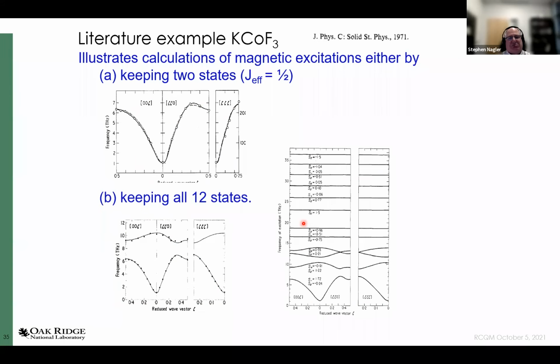So this is exemplified by this material, potassium cobalt trifluoride, seen here in some old literature. It behaves like a 3-dimensional Ising antiferromagnet. And it's not completely Ising, it's somewhat Ising, but you get a gapped spin wave spectrum, which you can interpret in terms of just a J equals a half model if I look at the lowest lying levels. But if I keep all 12 states in the lowest manifold and diagonalize that problem, I see a whole set of levels that comes up, and these can be measured.